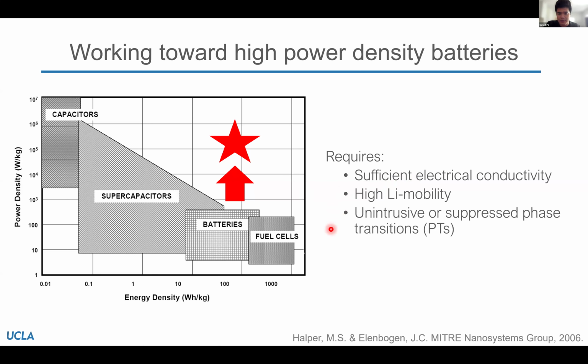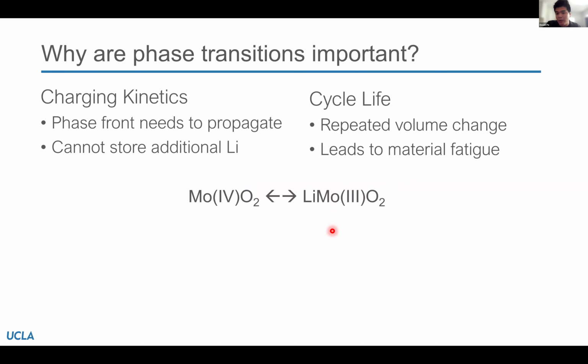To make a little more sense of this, we can look at how lithium-ion batteries react. What I have here is just a basic chemical equation. Here we're looking at rutile-like molybdenum dioxide, which I'll be talking about for the rest of the talk. We start out as MoO2 without any lithium present, with molybdenum in the 4+ oxidation state. Through electrochemistry, applying current or voltage to our cell, we can reduce our molybdenum to molybdenum 3+, and part of that reduction reaction is incorporating lithium into the structure to make LiMoO2.